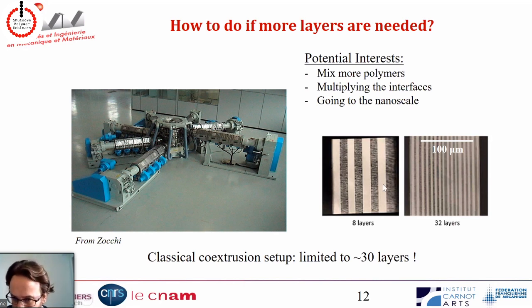So if I have 30 layers, I have something that looks like that, and my film looks like that. So in the thickness, you have 30 layers. The total thickness is about 100 micron or so, so each layer is a few microns. But now, what can I do if I want to have nano layers? And that's going to be the focus of my talk now.